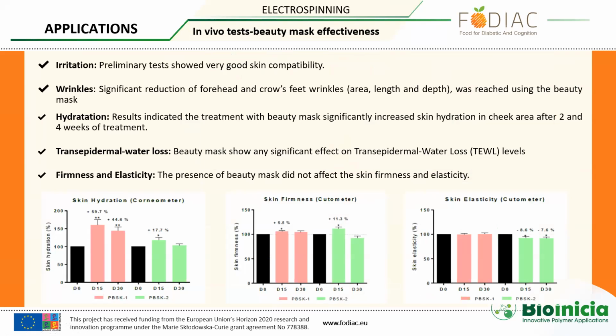But if we look at the other parameters as well, there are even significant differences just by looking at the treatment with the placebo, which is with the electrospun carrier, which may indicate that even just the topography of the placebo face mask itself, made with nanofibers, and perhaps as well the nature of the polymer it is made of, contributed as well. But overall, there was an increase in skin hydration, skin firmness, and even for the placebo, the elasticity was maintained.